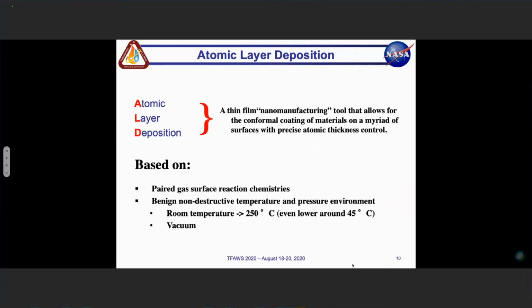So one technique that can be utilized in order to meet some of those requirements, which are proper step coverage and being able to deposit things uniformly, is this idea of atomic layer deposition. Atomic layer deposition is pretty much where we take that CVD process and we break it apart. Instead of introducing two gases at the same time, we introduce a single gas one at a time inside of our chamber. Only that particular gas reacts with your substrate, and that's known as a gas surface limiting reaction. Once all your sites have been reacted with, you can no longer have a reaction. Then you introduce a second gas.